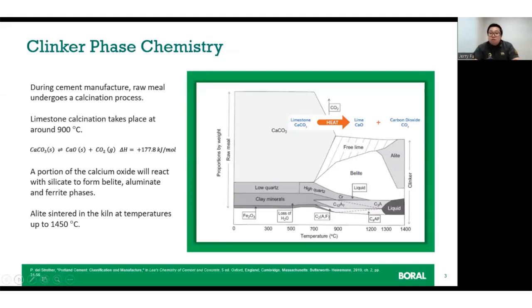As long as we don't change the raw material we use to make our grey cement, CO2 emissions will be unavoidable. To manufacture cement, the powder raw material is fed into the preheater tower and then the calciner. It gets heated and the calcium carbonate, the limestone in the raw material, undergoes a calcination process. The preheater consists of a series of cyclones through which the raw material is heated with the hot flue gas, and the calcination of limestone will take place at around 900 degrees. The chemical process can be described as calcium carbonate transforming into calcium oxide and CO2 gas.